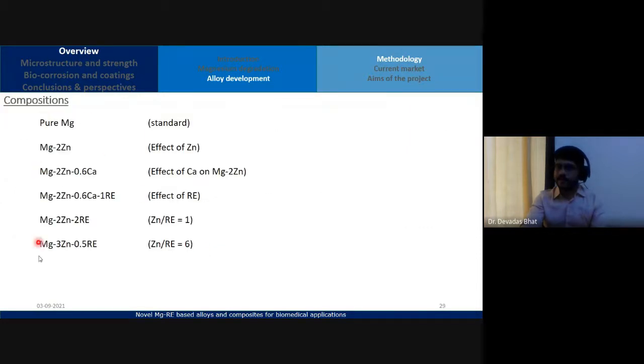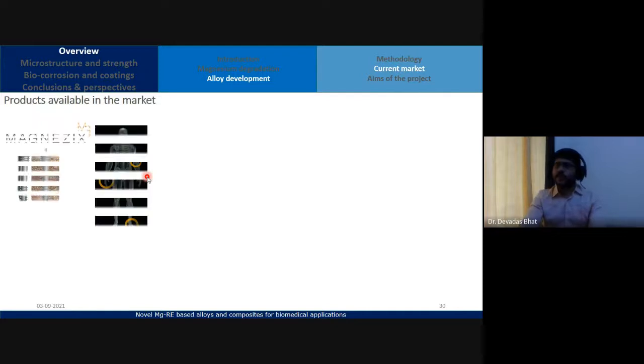Now these are the compositions that we have designed. We have taken pure magnesium, which is a standard. We have added zinc to study the effect of zinc, calcium to study the effect of calcium on zinc. Then we have added erbium to study the effect of erbium. Then we have designed two alloys such that their zinc to rare earth ratio here is 1, and here the zinc to rare earth ratio is 6. We designed it such that we wanted certain types of phases to form. That's the reason why we have chosen such ratios.